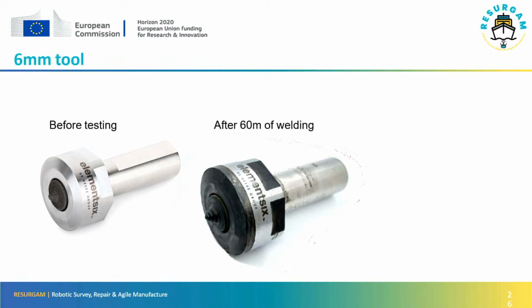That's what the tools look like before and after welding. Apart from going black because of the heat, they're still pretty much the same. What you can do with friction stir welding is you can actually use things like milling machines to do it as well. If you're not welding very thick material and the forces are low, I said that this process is like milling with a blunt cutter. You actually can convert milling machines to do this, which you'll hear about later.